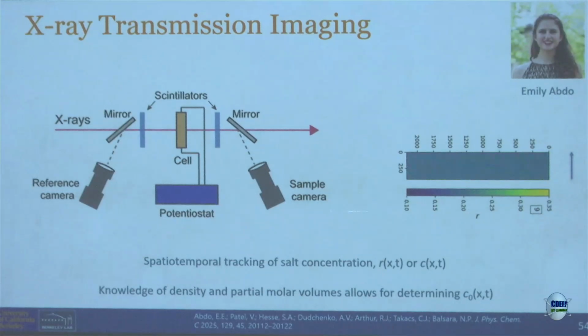And so this, of all the things I've shown you, and I've talked about concentration gradients, this is the first direct measurement of concentration gradient in exactly the cell that I was talking about. Okay. And there are no adjustable parameters. It turns out that the extinction coefficients of fluorine, lithium, et cetera, are all tabulated. So you just measure the extinction, and you get out the concentration.